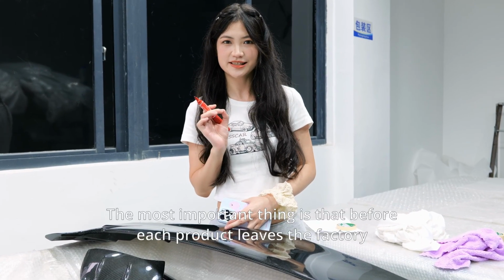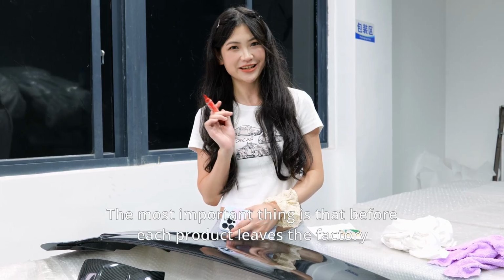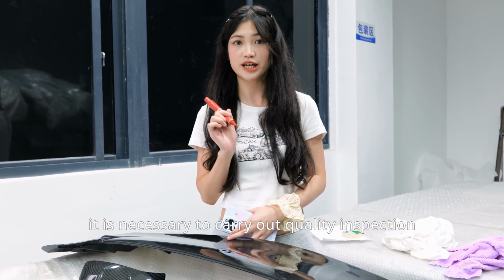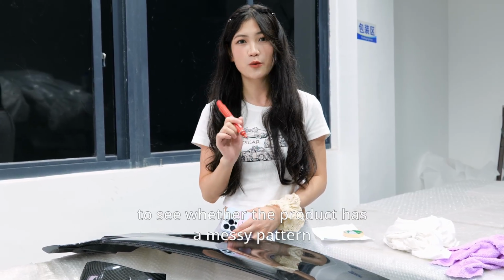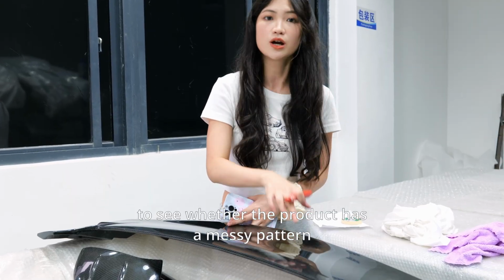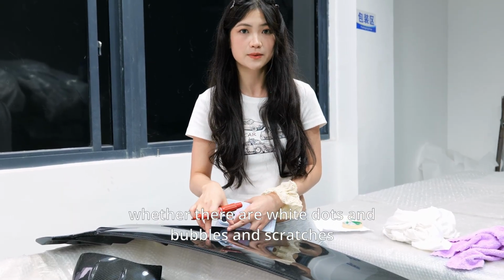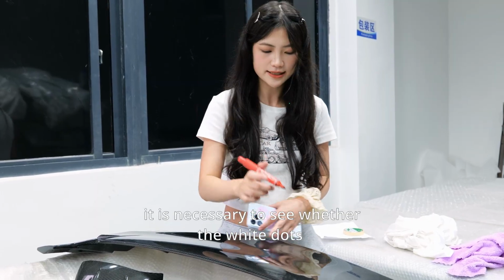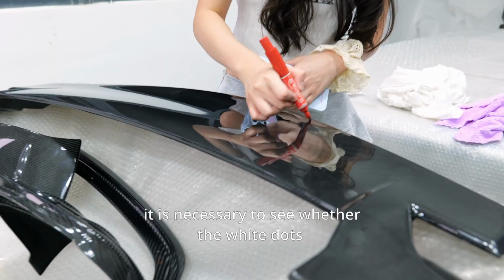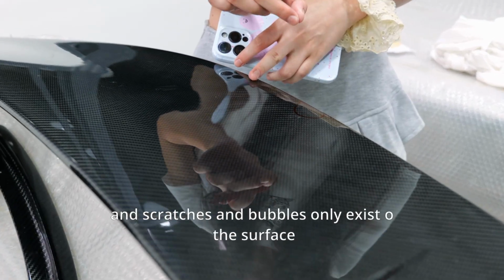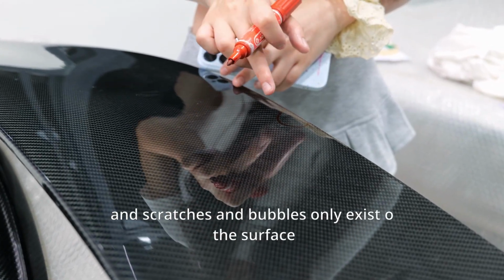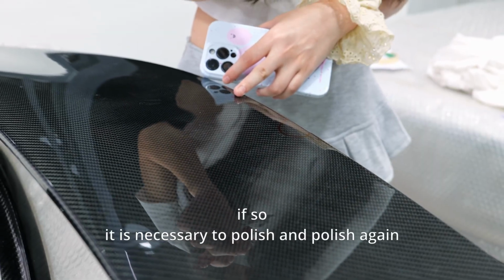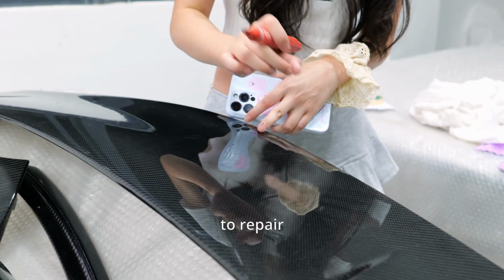The most important thing is that before each product leaves the factory, it is necessary to carry out a quality inspection to see whether the product has a messy pattern, whether there are white spots, burrs or scratches. If a similar situation is found, it is necessary to see whether the white spots, scratches and bubbles only exist on the surface. If so, it is necessary to polish again to repair it.